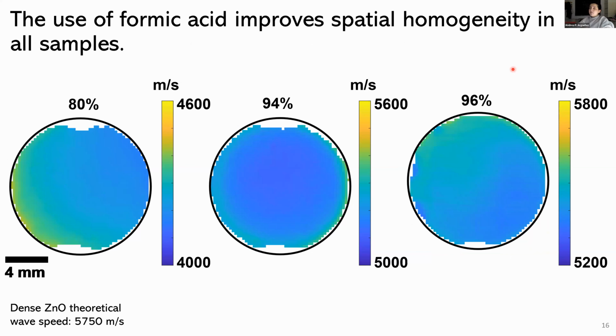So that's exactly what we did when we moved on to do formic acid instead of zinc acetate for that transient liquid phase. And what you see here, so again, the range is a little bit larger here for these samples at 600, but you see that there's much more significant uniformity in the samples. We don't have the large laminations that we were seeing before. So again, by characterizing the samples with ultrasound, we were able to identify some of the pieces that we could put together and ensure that we were getting a more uniform sample.